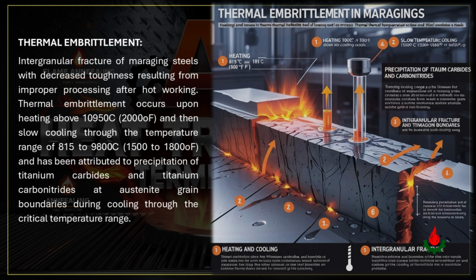Thermal embrittlement. Intergranular fracture of maraging steels with decreased toughness, resulting from improper processing after hot working. Thermal embrittlement occurs upon heating above 1,095 degrees Celsius, 2,000 degrees Fahrenheit, and then slow cooling through the temperature range of 815 to 980 degrees Celsius, 1,500 to 1,800 degrees Fahrenheit, and has been attributed to precipitation of titanium carbides and titanium carbonitrides at austenite grain boundaries during cooling through the critical temperature range.